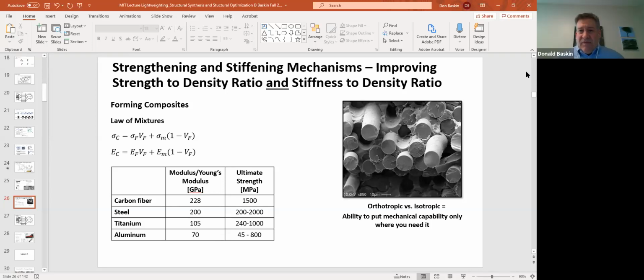So the final strengthening mechanism I'm going to talk about here is using a composite. I'm sure a lot of you have seen carbon fiber composites. Like me, it may be what really piqued your interest in material science to begin with. Carbon fiber uses two different materials in order to increase the strength. The carbon fibers themselves are incredibly strong and incredibly stiff, but on their own, they're kind of like wet noodles. You're not going to do much with them in any kind of bending if they're not consolidated, held together by a matrix. The matrix, in most cases for really high strength carbon fiber, is epoxy. The epoxy serves to transfer the load from one fiber to the next. And through making this composite of carbon fiber and epoxy, you're able to get a very, very strong material.